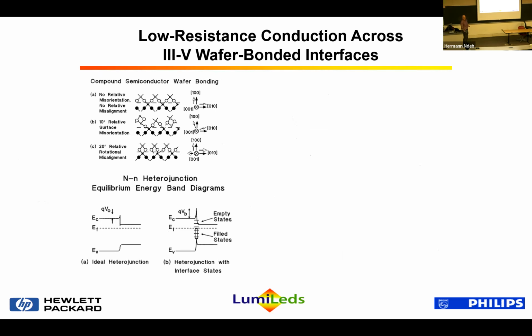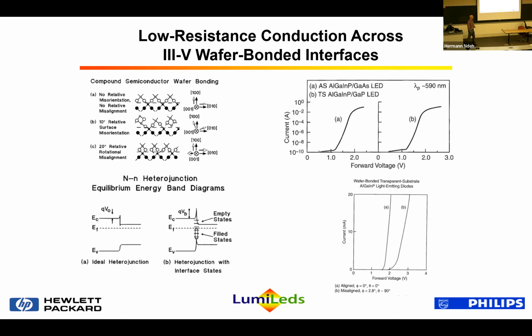What we think is happening here is that, by having the different surface misorientations, you create additional defects or interface states. And those interface states basically pin the Fermi level and give you an additional barrier at the interface. And we would see this also in LEDs. So an LED that was fabricated with no misorientation could operate at good low voltages, whereas for a misoriented device, we'd see a significant additional voltage drop. In a well fabricated device, we would also see no difference in the IV characteristics or where the N=1 to N=2 transition occurred between a non-bonded device and a bonded device. So we're not introducing any additional defects in the device by virtue of the wafer bonding.